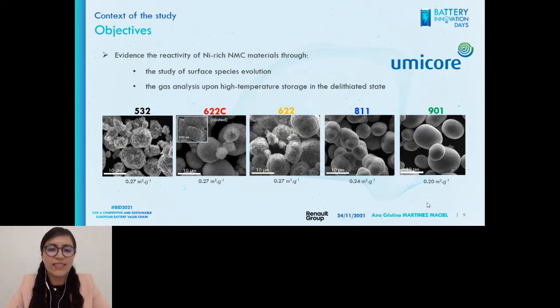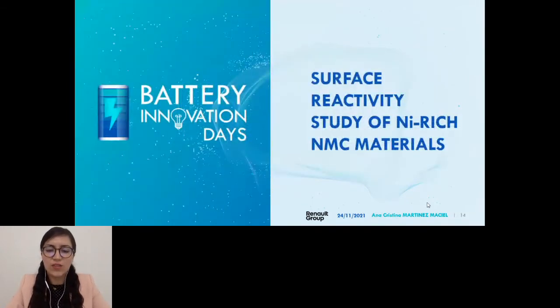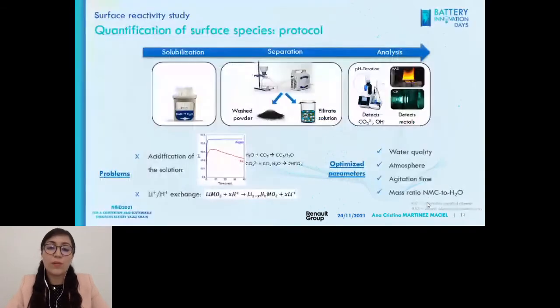Let's go with the first part of the results. I wanted to study the surface reactivity of these materials, so I needed a protocol that didn't exist in an optimized way. It basically consists in solubilizing the surface species on NMCs, separating on one side the washed powder and on the other the solution containing the surface species, to finally analyze the solution either by pH titration that detects carbonates and hydroxide, or by inductively coupled plasma and atomic absorption spectroscopy.